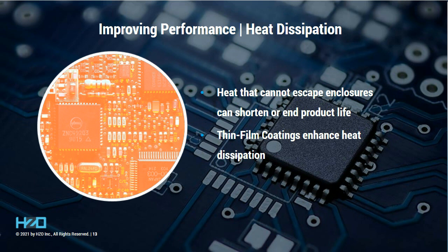And in fact, just a tiny little bit of increase in temperature, 8 to 10 Celsius, over the maximum rated temperature shortens the service life of the semiconductor by roughly half. This is an important point to consider. If it's warmer than it should be, and not much warmer, but as I said earlier, only like 8 to 10 Celsius warmer, the semiconductor life can be as little as half. So sometimes we need to service the electronics. We need to connect something or put an SD card in it. So we need to open up this enclosure. So each time we open up this enclosure, we change the atmosphere inside. So this also can potentially play against us.